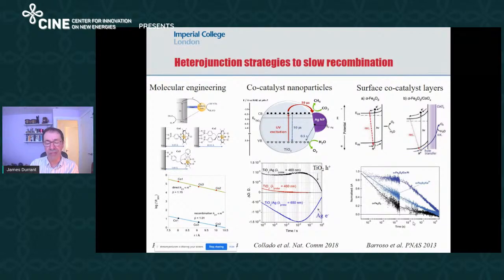These are all examples around making junctions. Essentially, it's the same idea as in photosynthesis, or the junction between a dye and titanium dioxide in a dye cell, or the donor and acceptor in an organic solar cell. These are approaches where you separate the charge across an interface. In this case, on the left, charge is separated by putting a molecular catalyst on the surface. And the more you move the molecular catalyst away from the surface, the longer the lifetime is for the recombination, which means you gain more lifetime if you move the charge further from the surface.